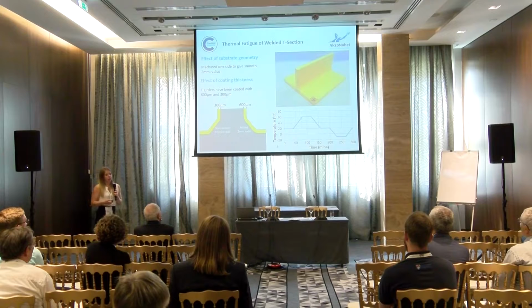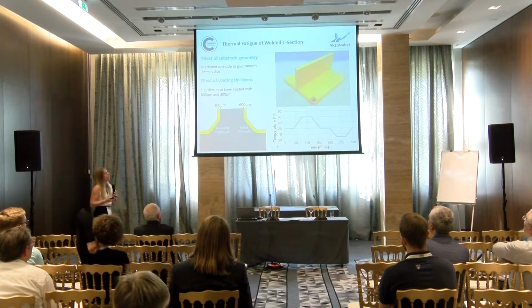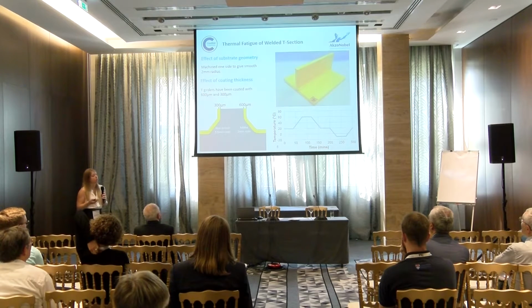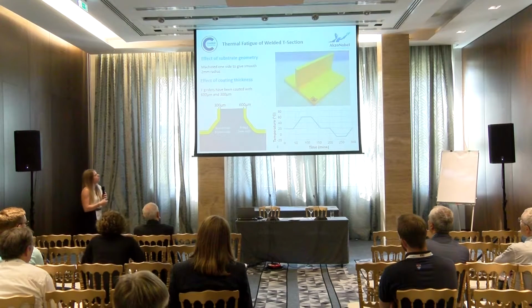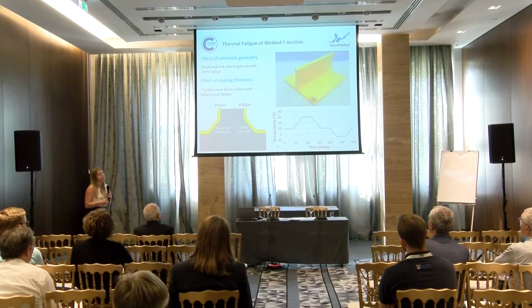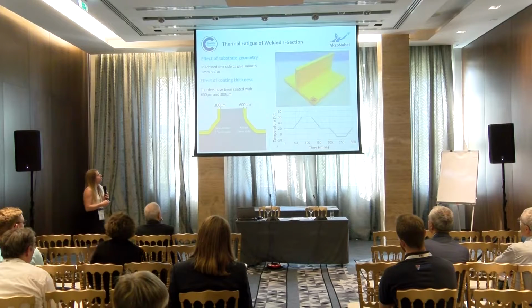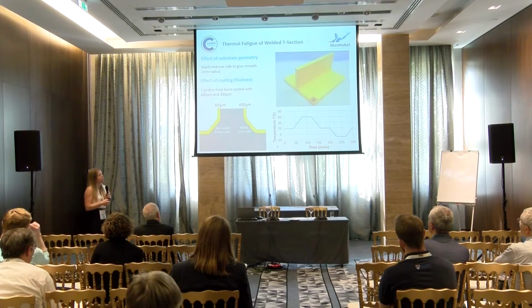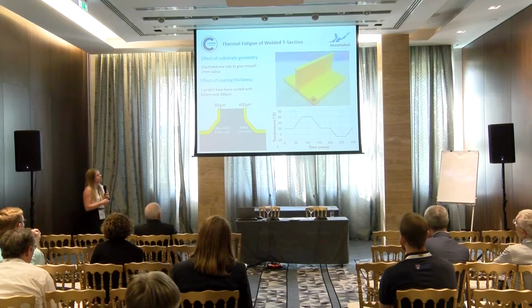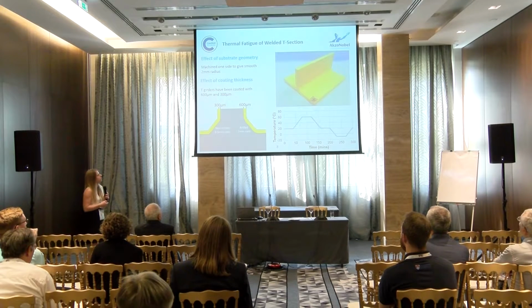So just a little bit about the thermal fatigue testing that's been carried out. As we saw in the previous image with all of the nasty corrosion on it, the worst failure is happening in these welded T-section areas. Therefore, a welded T-section of structural steel was chosen to be the substrate. In order to understand the effect of substrate geometry, one side of each T-section had its welds milled to provide a constant 2 millimeter radius along each weld length, while the other side was left as welded. So this gives us two conditions, a milled and a non-milled surface.